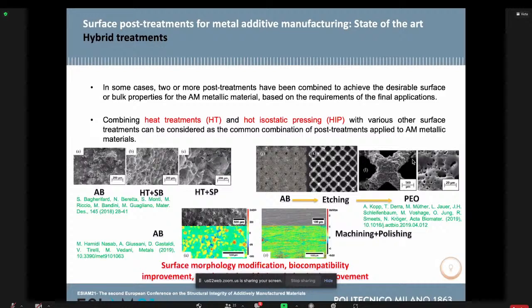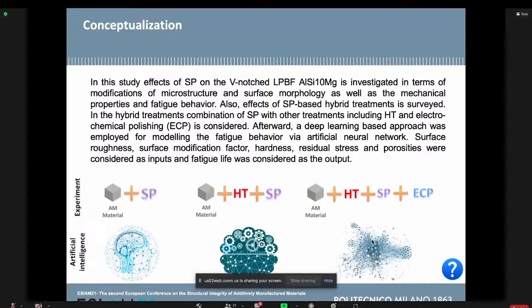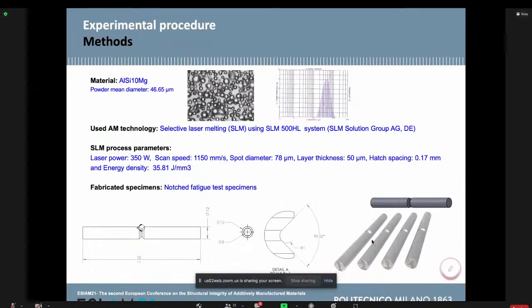Also, about the hybrid treatments, it was found that different treatments such as heat treatment or hot isostatic pressing (HIP) combined with other surface treatments can be used on the materials to gain desired surface or bulk properties. For example, in some works a combination of heat treatment and sandblasting, or heat treatment and shot peening, was used, and in other works a combination of etching and PEO. Also, a combination of machining and polishing has already been applied in the literature. In this study, we investigated the effects of shot peening, heat treatment, and electrochemical polishing, individually and also combined together, on the fatigue behavior of notched fatigue samples.